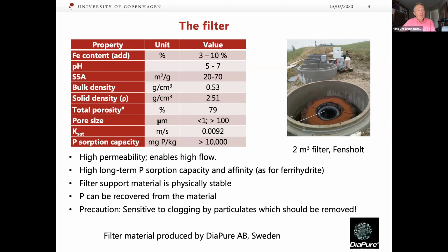It has a relatively high P storage capacity. The idea here is that phosphate that is sorbed on the external surfaces of the particles is moved into the internal space and stored within the granule, and then the sorption sites on the surface are continuously renewed. It's a physically stable material, but of course it can dissolve under reducing conditions. We can recover P from the material.